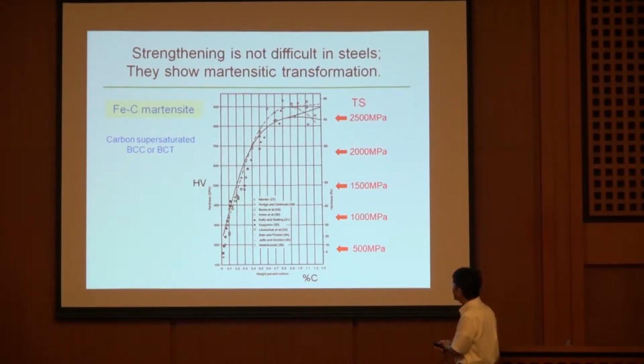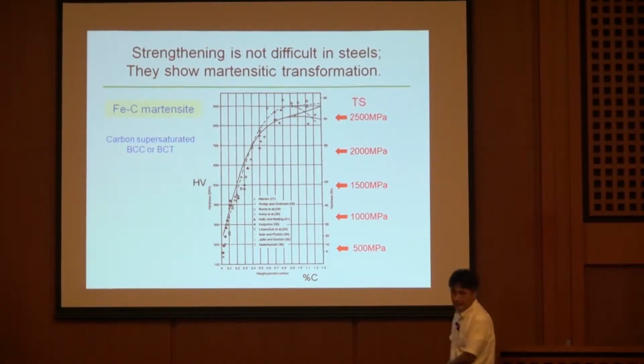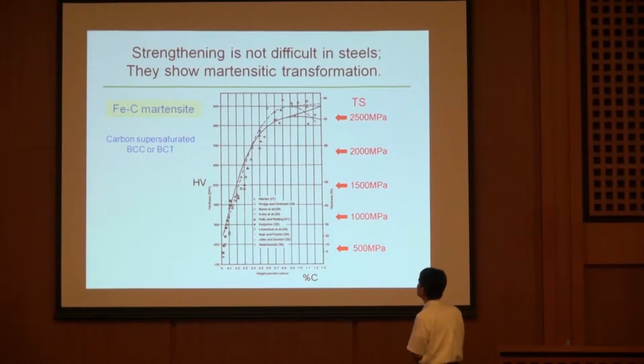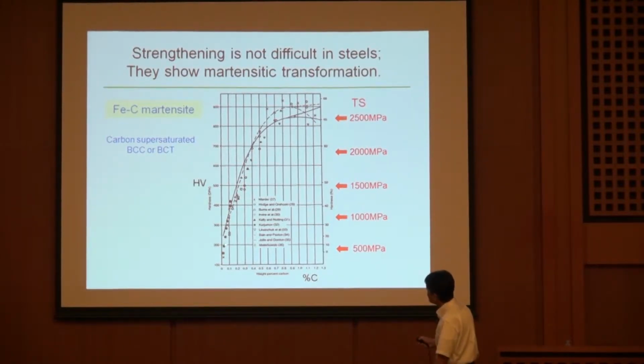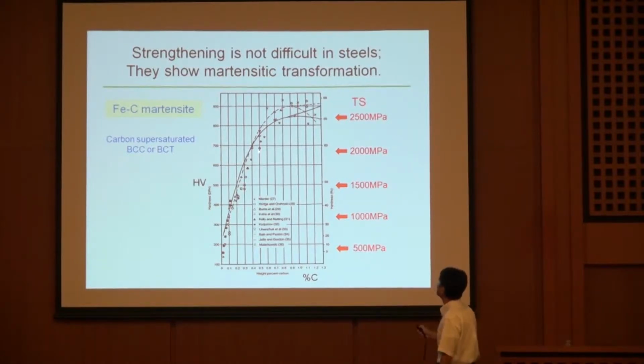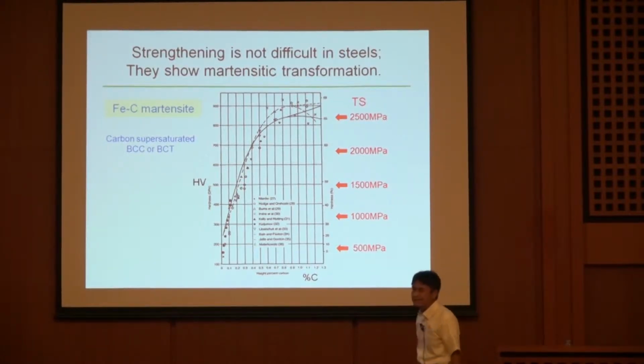This is the hardness here, and this is the carbon concentration. This is the data of iron-carbon binary martensite. Its strength and hardness increase sharply like this. And if you get a carbon content of 0.4 mass percent, then you can get the strength level of 2 gigapascal.